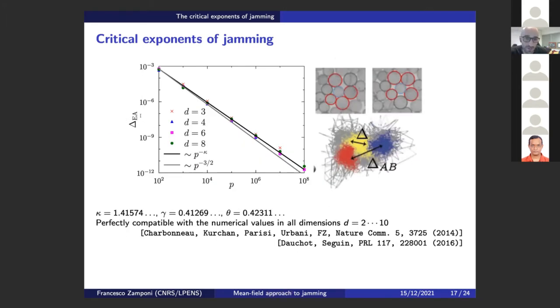So this is a plot of the plateau as a function of pressure. Now we have hard spheres. The hard spheres are colliding, and the pressure comes from these hard sphere collisions. You are approaching jamming from the low density phase where the system has no overlaps, but still, because it's thermal, you have collisions. The pressure is finite, and when you reach jamming, it diverges because they collide a lot. So this is why pressure is diverging here. Jamming is when pressure is infinite.